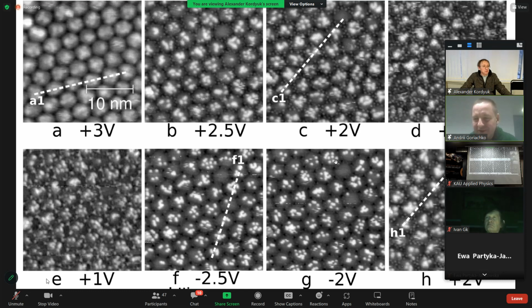In image D, you can see some remaining brighter spots. These are remaining spots within the graphene layer, which are actually imaged in the STM. In between them, there are a lot of smaller circles, and these are just the germanium atoms. We have checked that the interatomic distance between them is typical for the germanium substrate.